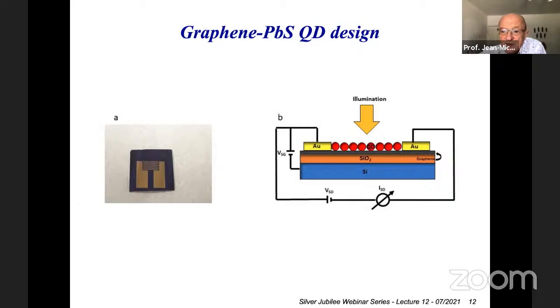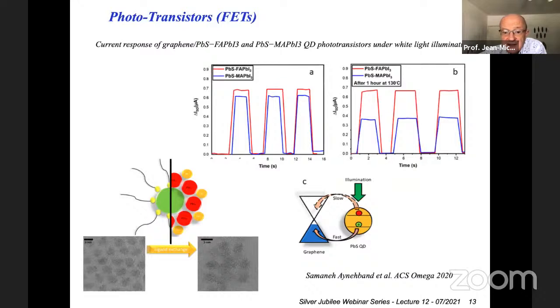And then we deposit on top some quantum dots, and the quantum dots provide the absorption. And here is an example. The quantum dots are lead sulfide, which absorb in the infrared. And when they are under white light illumination, the quantum dot absorbs the light and generates electron hole pairs, which shift the Fermi level of the graphene and change the conductivity. And then using different ligands, we worked on the ligands. Samaneh was doing the work, in collaboration with Sharif University, in the team.